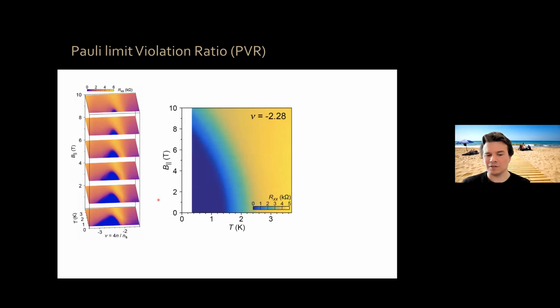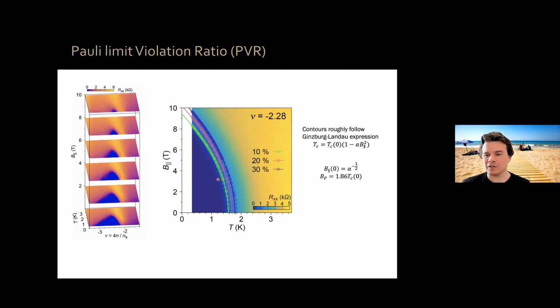So this is one of these cuts, continuously as a function of parallel field for a given filling factor, for a given density, okay? And you can see that we can plot here equal resistance contours, 10%, 20%, 30% of the normal state resistance. The same thing happens for 50% or for BKT, for the transition to 0, exactly, okay? We can look at the following.